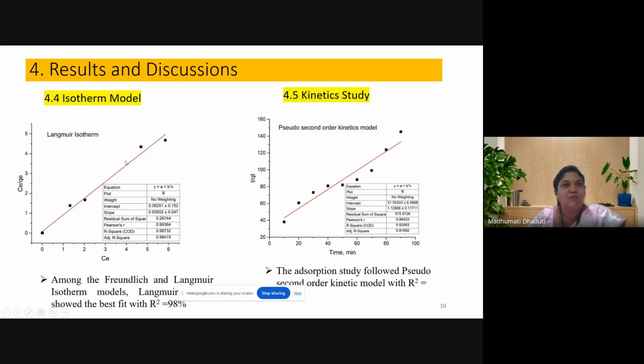And among the isotherm models studied, the best fit was the Langmuir isotherm model with an R-square value of 98%, which showed that monolayer adsorption happened there. And the pseudo second order kinetics model was the best fit as far as the kinetic study was concerned.